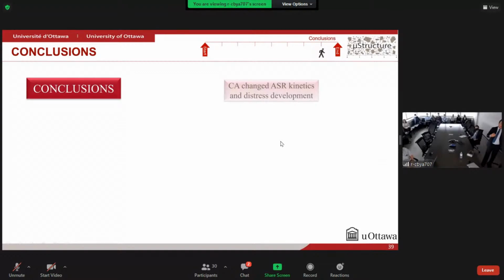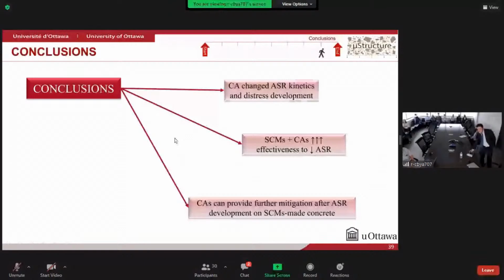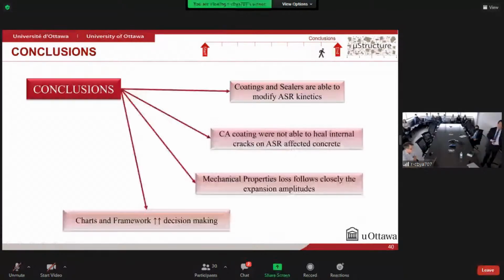Also, the mixtures in which we combine SCMs with crystalline admixtures were the most effective mixtures against ASR development. And as I asked in the beginning of this presentation, whether self-healing could provide further mitigation of ASR, it was proved that they can indeed provide further mitigation after ASR development. It starts on SCM-made concrete. And then finally, coatings and sealers were able to modify ASR kinetics. However, once we use the crystalline admixtures as a surface treatment, this material was not able to heal internal cracks in ASR-affected concrete.